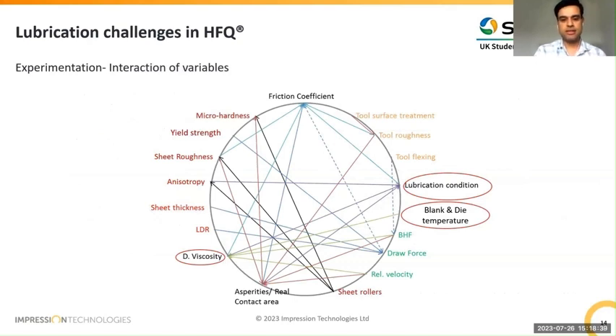And the reason for that is this complex interaction of variables. This is a busy slide and a rather confusing diagram, but as I'll try and explain, this side has all the sheet properties: the sheet surface roughness, the strength of the sheet at high temperature, and the temperature is dropping, and its hardness. And there are some tool parameters such as the coating on the tool, roughness, and the elastic deflection of the tooling. Then there are some process parameters such as the force and the relative velocity, and then there is blank and die temperature. But all these parameters are interconnected and their interaction is dynamic, and I wouldn't say random, but predictable yet very hard to predict. And that's one of the reasons that the experimentations are not repeatable. And hence there's a problem in how you evaluate a lubricant that can not only last one part, but an entire production run of a few thousand parts.